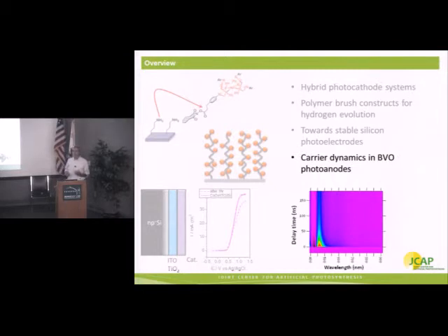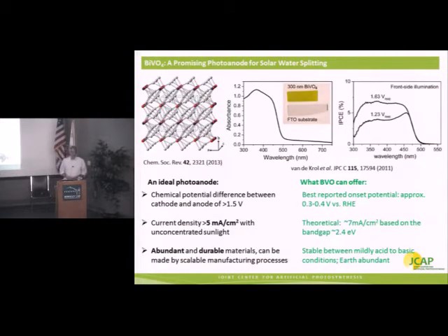That requires a means of stabilizing its surface against corrosion in the harsh electrochemical environment. Another approach is simply to use a semiconductor that itself is stable under these conditions. So that'll bring me to basically the final portion of my talk, where I'll discuss bismuth vanadate, which is a ternary oxide semiconductor that's promising for water oxidation, or as a photoanode. Okay, so this material, it has a number of different phases. The phase we're interested in is the monoclinic phase of bismuth vanadate, which has a band gap of about 2.3 or 2.4 electron volts.